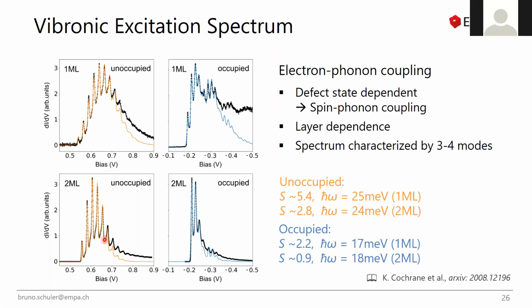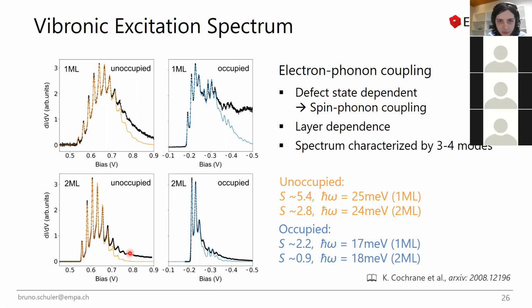So you were saying that you would expect an increase of the width with energy. Right. Why is that? Well, it's just like the Fermi liquid case. At higher energy, you have a shorter lifetime of states, perhaps. If the lifetime doesn't change, then it is probably limited by interactions with another process that is really controlling the lifetime, not the intrinsic width. And so in that case, you should not see much of a difference.